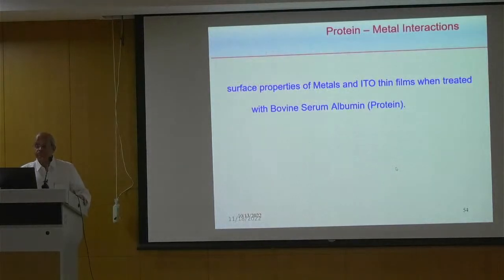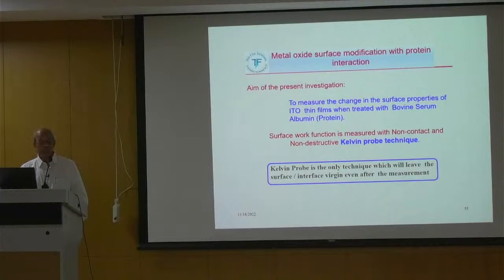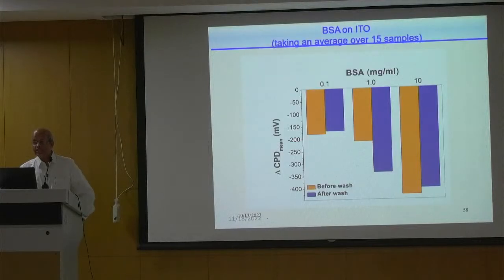There is a correlation. So coming back to our experiment, we have taken ITO and titanium. We have treated them with bovine serum albumin, and we have seen how it changes the surface work function. ITO is indium tin oxide grown by the magnetron technique. We have taken about 15 samples, and you see when 0.1 milligram per milliliter of bovine serum albumin is on ITO, the CPD changes like this, all negative, before wash and after wash. Before wash it shows about minus 175. Even after wash, that still remains on the surface. It means it is sticking there.